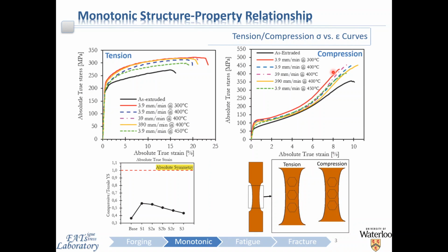Both the yield and ultimate strengths, as well as the ductility of the material, were improved due to forging, with lower temperatures and higher forging rates being favorable for higher strengths and higher ductilities. In compression, twinning is very active, as can be seen in the stress strain plot illustrated on the right. This results in a large disparity in the response between tension and compression, known as yield asymmetry, which is a phenomenon that is very common in most forms of magnesium alloys, and the cause is linked to the hexagonal close-packed